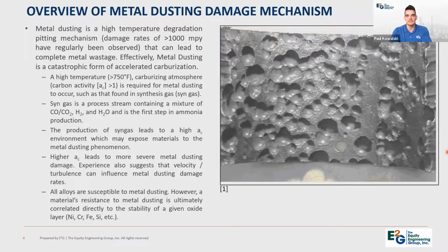And typically the higher the carbon activity, or that is the amount of carbon monoxide available, generally leads to higher damage rates. And additionally, experience suggests that damage can also be influenced by velocity or turbulence, and consequently accelerating the damage rate as well. So with metal dusting, all alloys are really susceptible to this mechanism. There isn't one material that has 100% resistance, but really the resistance of a material to metal dusting is directly correlated to the stability of the oxide layer.